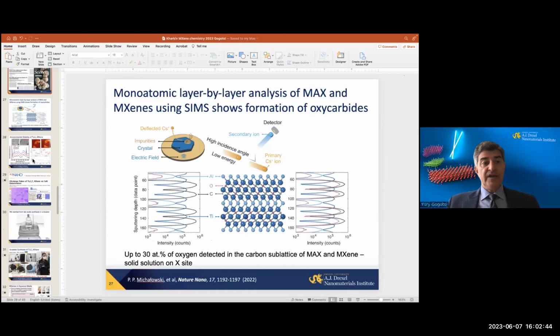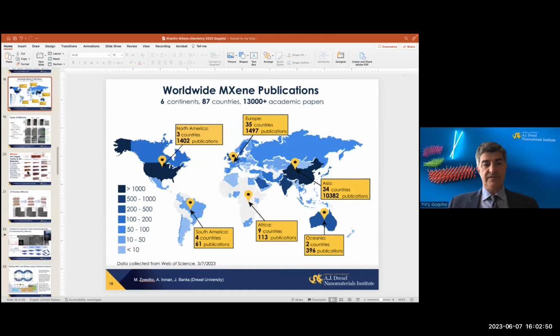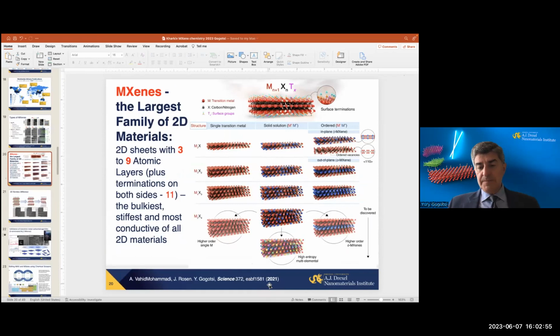Second, you're absolutely right that there are many reports in the literature on different MXenes. Some of the MXenes have been made, some not. For example, when we published this paper in Science 2021, high entropy materials were predicted but not reported yet. And they have been made and published since then, in the last 2 years. Many others. Chromium carbide MXenes, we could not make. We're still working to make it because of very interesting predicted properties. I don't think reports on chromium carbide are correct. I think it's largely oxide that was made, layered chromium dioxide. It got oxidized.